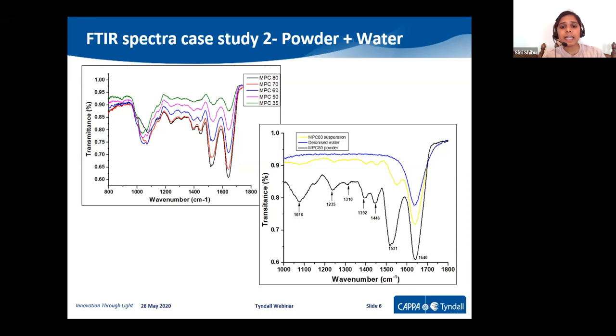As it is getting diluted, the casein proteins will get dissolved in the water and disintegrate. So dissolution will happen, and basically it is disintegrating the casein structure. So in that case, the absorption from this sample will be less. So we can consider that's how the dilution process is. As the dilution increases, as the time lapses, there will be a very evident difference in the FTIR spectra.